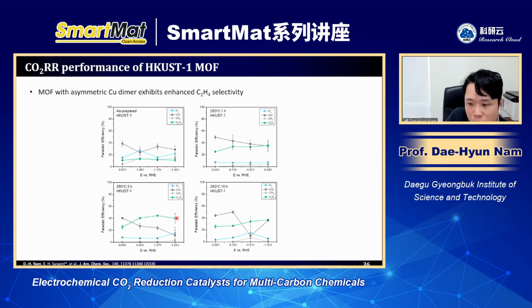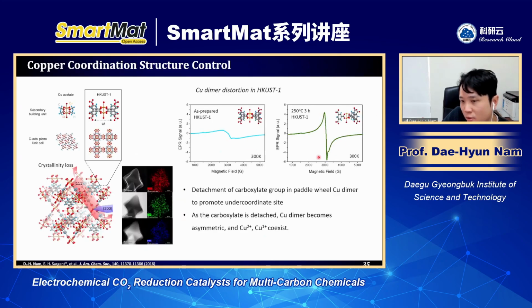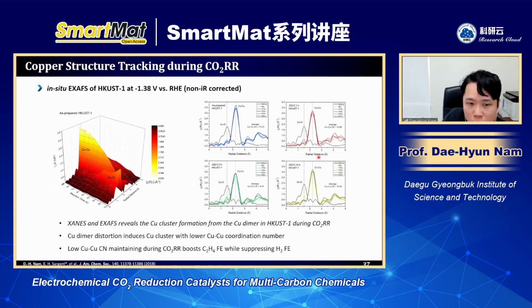So it means there could be some reason why this asymmetric copper dimer is effective for ethylene production, although they started from the same material. So we measured in situ XAS, which I showed before, and compared the copper-copper coordination number. Interestingly, as the copper dimer became more asymmetric, the copper-copper coordination number decreased. It means the symmetric copper dimer induced a high copper-copper coordination number, but the asymmetric copper dimer induced a low copper-copper coordination number during CO2R. So we could find a relationship between the coordination number and ethylene production.